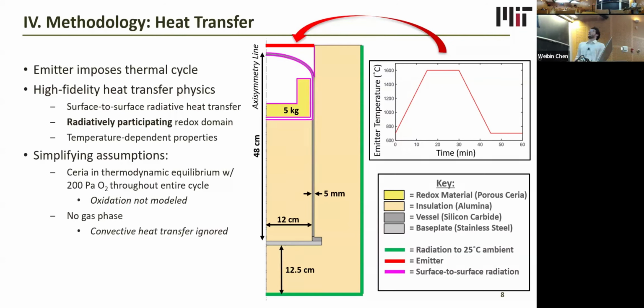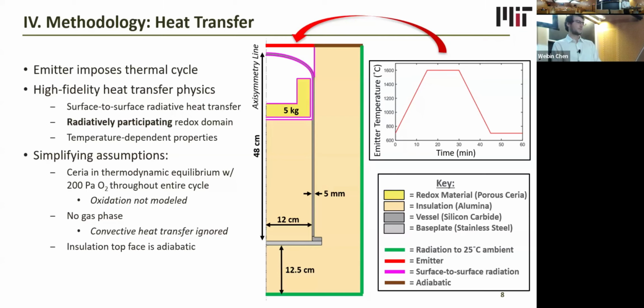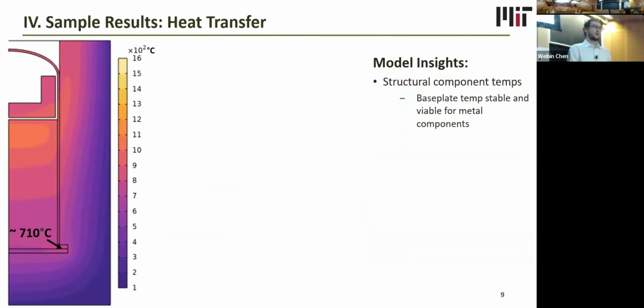We take some simplifying assumptions in our modeling. We're assuming that ceria is always in thermodynamic equilibrium with 200 Pascal oxygen partial pressure throughout the entire cycle. So this means that the oxidation phase is not going to be completely resolved. And we also don't include gas-based physics. So we're assuming that radiation is the dominant form of heat transfer. The top face of the insulation is also assumed to be adiabatic because it's always going to be facing another reactor. So here's some sample heat transfer results.